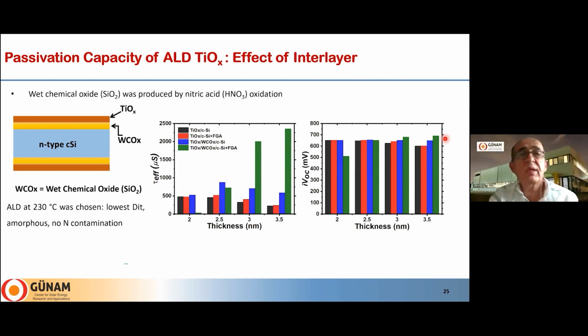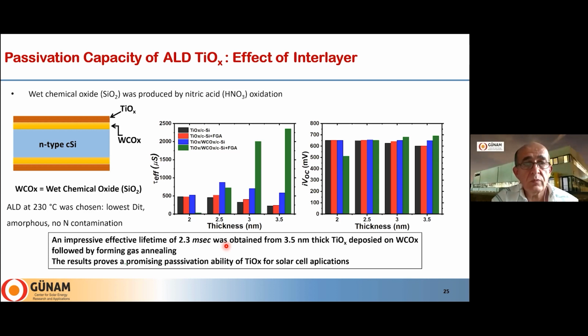But unfortunately, we couldn't fabricate a solar cell with this device because our ALD system broke down after these experiments, and we are waiting for the repair of this device. I have already mentioned that an impressive effective lifetime was obtained with a 3.5 nanometer thick titanium oxide layer.